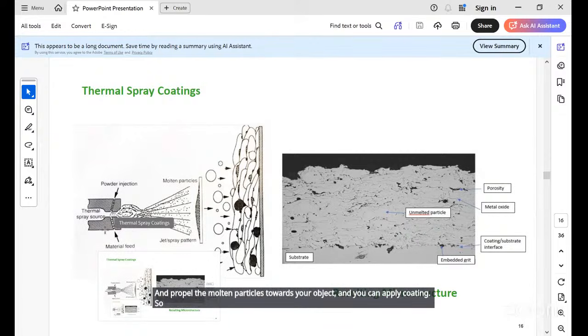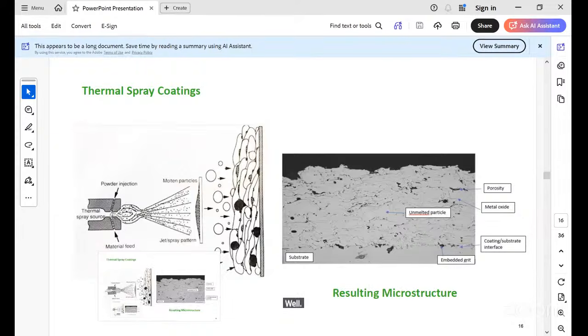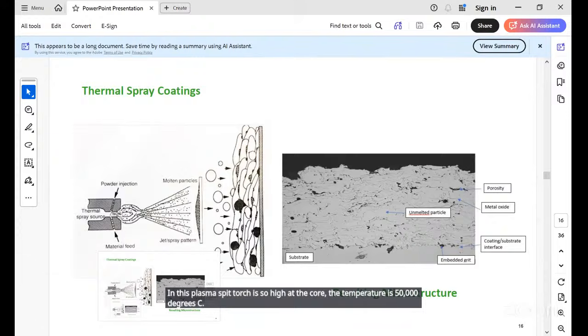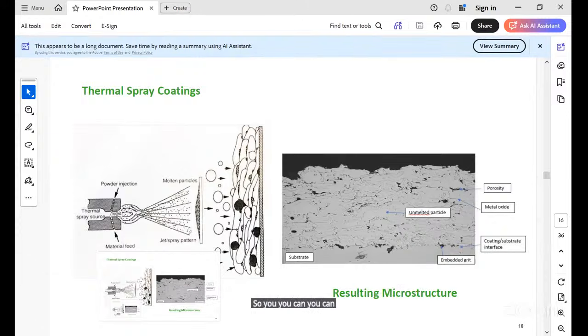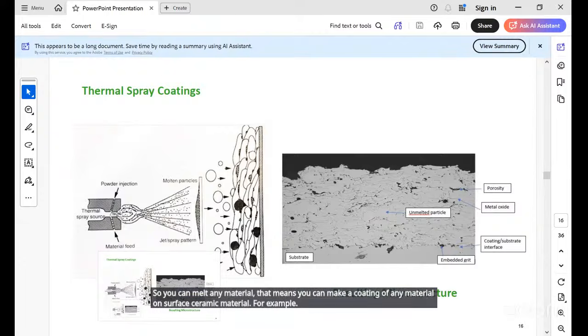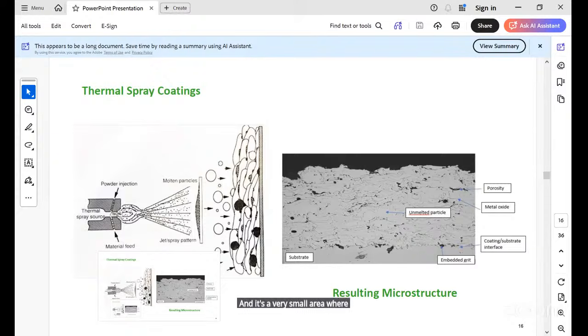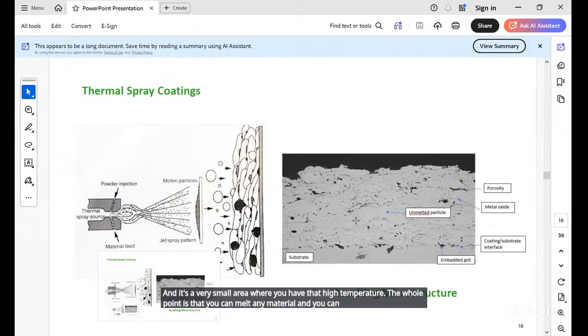The advantage here is that the temperature of the arc in this plasma spray torch is so high. At the core, the temperature is 50,000 degrees C. So you can melt any material. That means you can make a coating of any material on a surface, ceramic material, for example, which has a very high melting temperature. You never need 50,000, but in the core the temperature is 50,000. So you need to have water cooling and all those things. And it's a very small area where you have that high temperature. The whole point is that you can melt any material and you can make a layered coating.